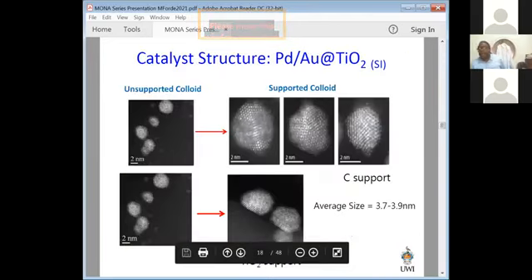And I wouldn't show that data, that has to wait till publication, whenever we finish that work. But I will show you the data on the materials and what they look like. So here we're looking at the colloids. This is the gold palladium system that Lokesh published in Science, works very well. You can see that this is the colloid before you put it on the supports, when you make it in solution, right? When you put it on carbon, it retains the shape more or less.